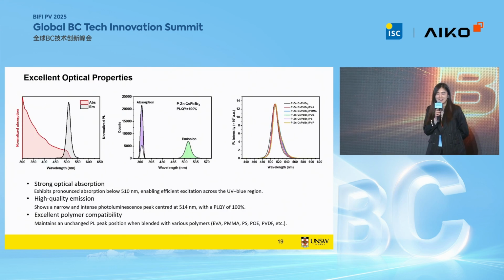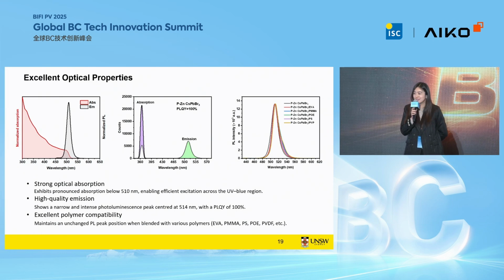These nanoparticles show excellent optical properties. You can see they show very strong absorption below 510 nanometers, and also a very sharp and narrow emission peak in the visible. There's one term we use to assess how efficient this down conversion process is. It's called photoluminescent quantum yield, PLQY. It's very difficult to make your material have 100% PLQY, because that means for every 100 photons coming in, you have 100 photons coming out. And we can successfully synthesize our material with 100% PLQY. And this material can literally mix with all kinds of commercial polymers without any problem.